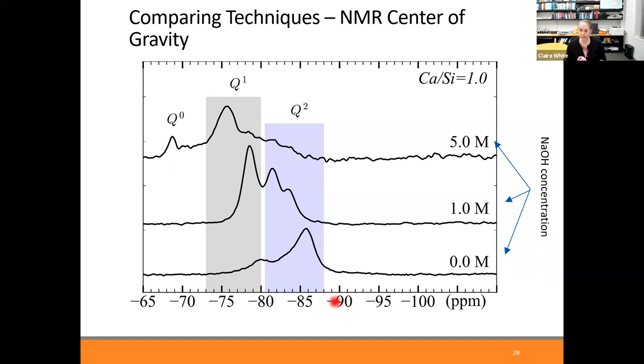This is silicon NMR. And the spectra give an indication of what Q exists for the silica units. So here in this region, it's Q0. In this region, it's Q1. In this region, it's Q2. We made a gel using the starting composition of calcium to silicon of 1, and we synthesized the gel in different sodium hydroxide concentrations: no sodium hydroxide, 1 molar, 5 molar.